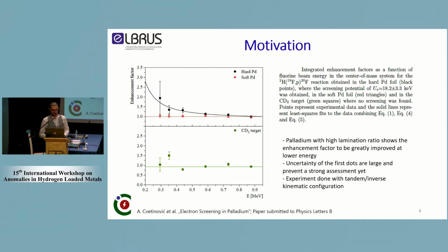This is of great interest for me, especially because at the beginning of the cold fusion explorations, we had a lot of people using lamination technique on palladium samples, palladium sheets, to increase locally the quantity of defects. These defects then were acknowledged to be producing and generating better results in terms of energy production in calorimetric experiments.